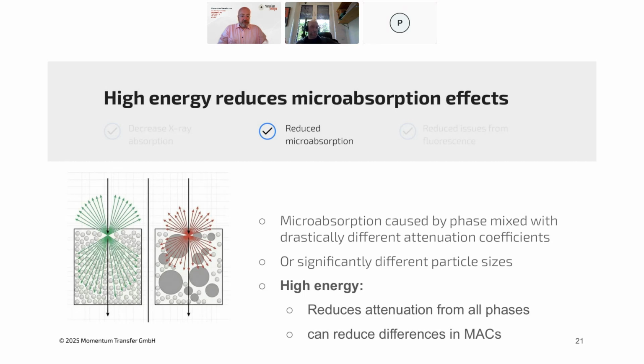Even if you go up in energy and all your mass attenuation coefficients go down, there can still be some differentials between them, and you can still get microabsorption effects from that. However, the amount of absorption from all those phases is a much lower percentage, and so this is having a lower significance, and also the differences can kind of even out a little bit at higher energies. So that also can reduce this effect, which is very good.